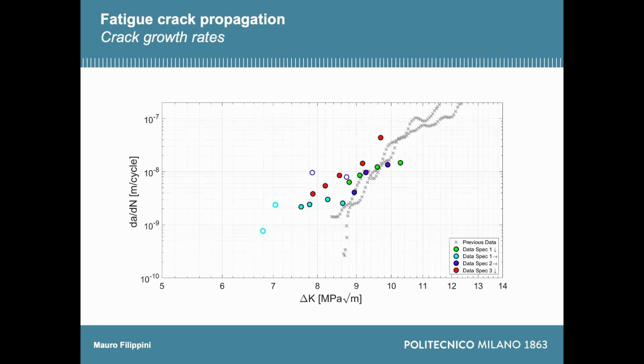Okay, so now we conducted a few years ago some conventional tests on CT specimen with the same alloy. And these are the gray dots on the Paris diagram that you can see here. And these are the new results conducted with this unconventional sub-size specimen. And you can see that you can observe propagation below the long crack growth threshold. So the long crack delta K threshold is about here, between, let's say, 8.5 and 9 megapascal square root meter. And you do have some propagation also here with the short cracks.